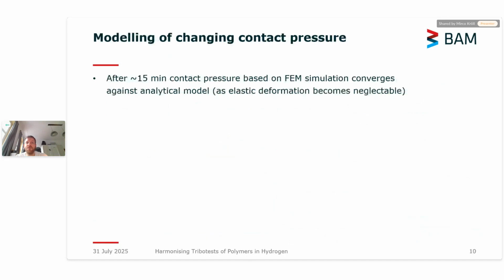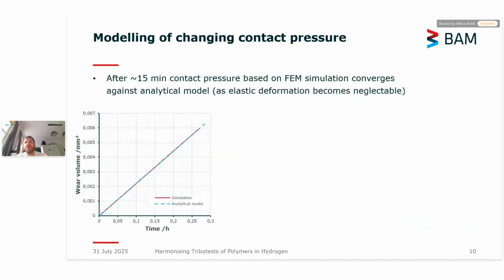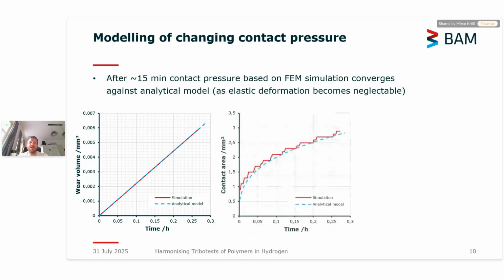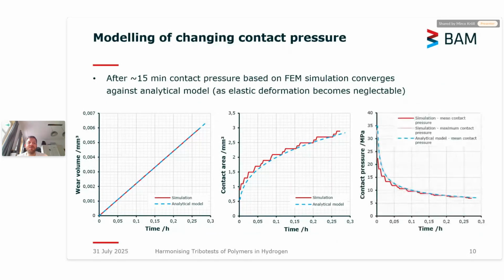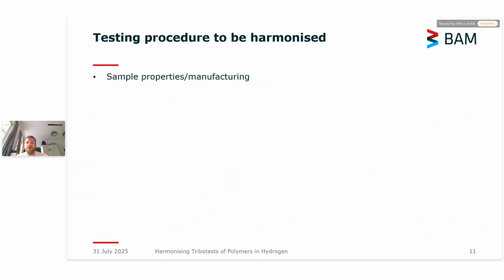If we did that, we figured out that after 15 minutes, both models converge to one another. So they are both comparable after 15 minutes. The wear volume and the time, of course, are the same. If you plot the contact area over time, you can see that they converge after 15 minutes, and the contact pressure at the end is roughly, here it's just plotted for 0.3 hours, a third of an hour. If you extrapolate that to 1 hour, you end up at roughly 5 megapascal, which is the application. So at the end of the test, we are near the application we want to see.